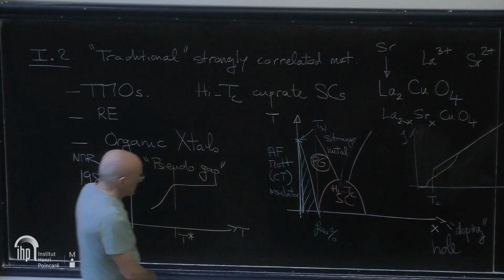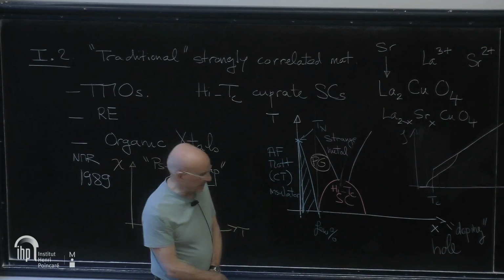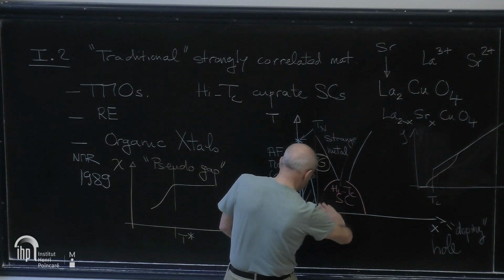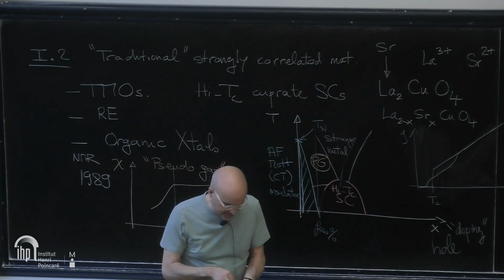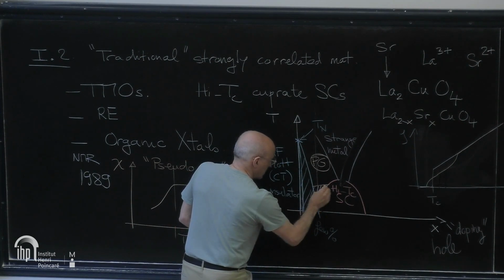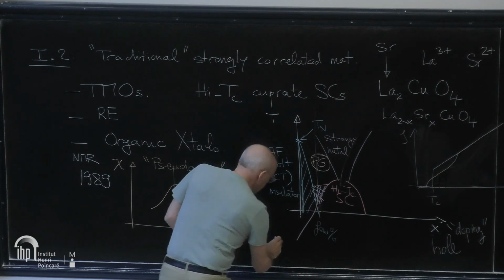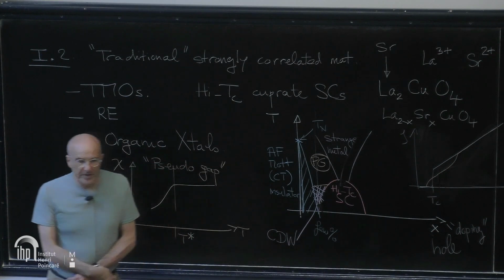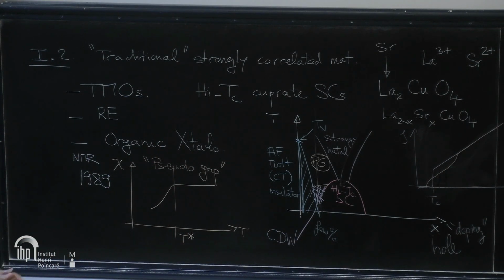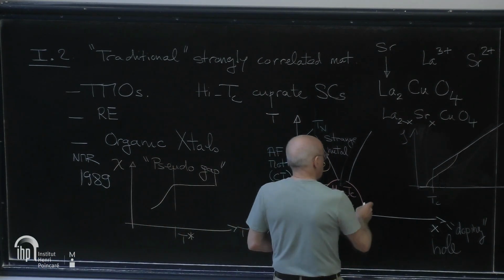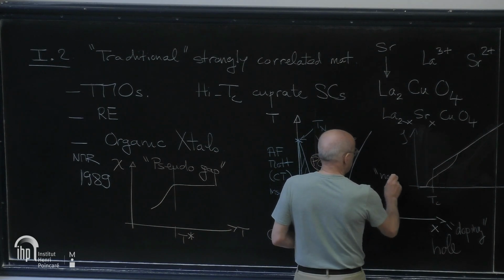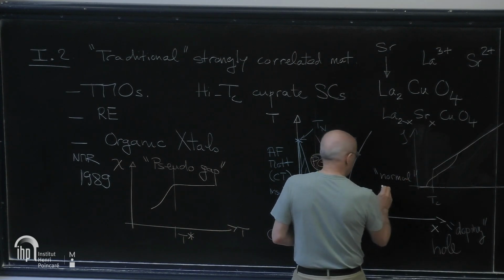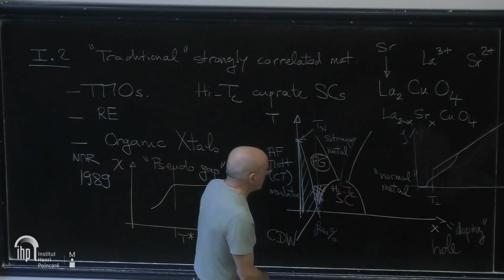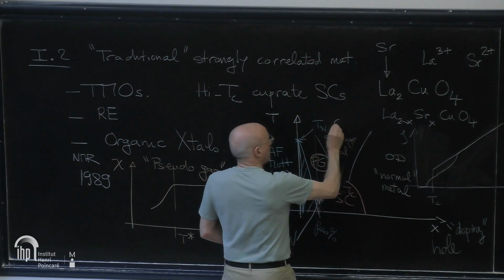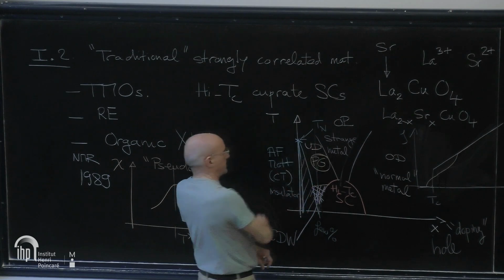Now, there are additional complicated phenomena in this system, which I barely have the space to draw on this diagram. But here, there is a regime in which charge density wave appears. So the local charge density is modulated in space. And here, there is a regime of somewhat more normal metal. Not quite, but more conventional, let's say. This regime is called the overdoped regime. This is called the optimally doped regime. And this is called the underdoped regime.